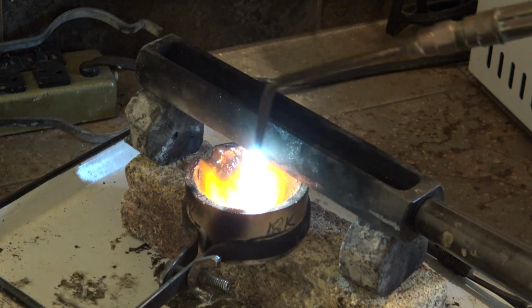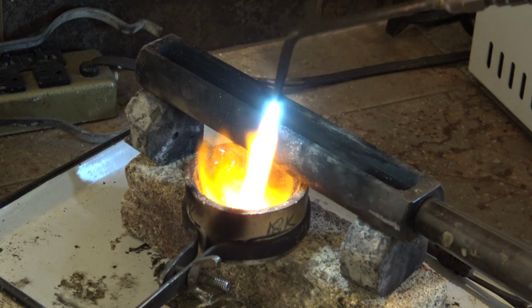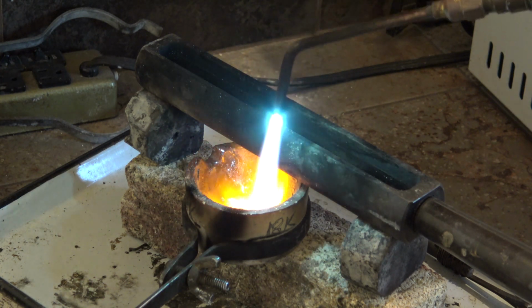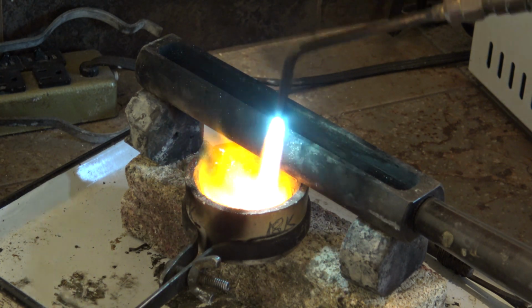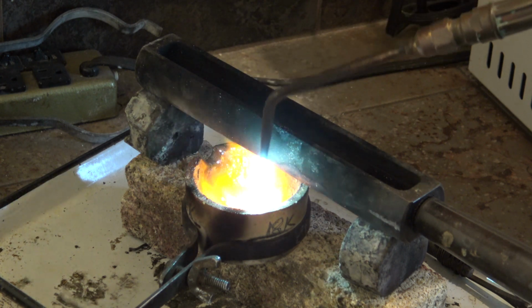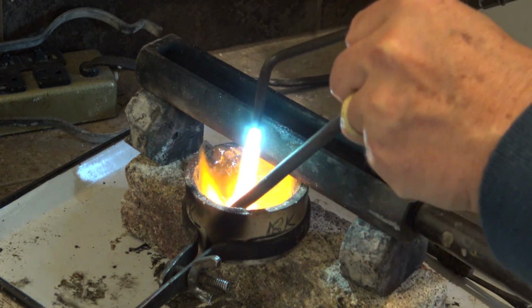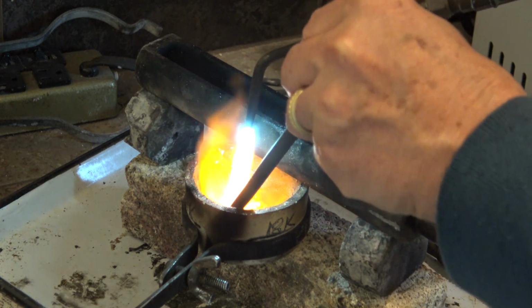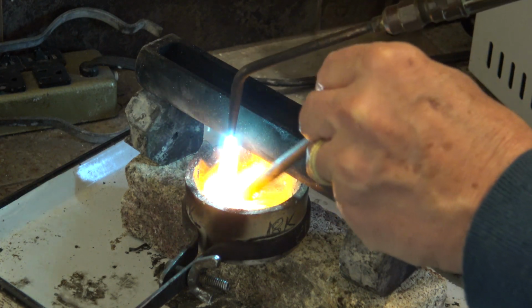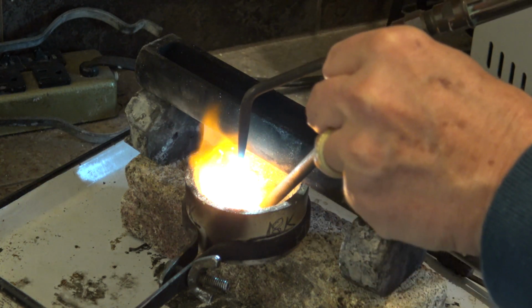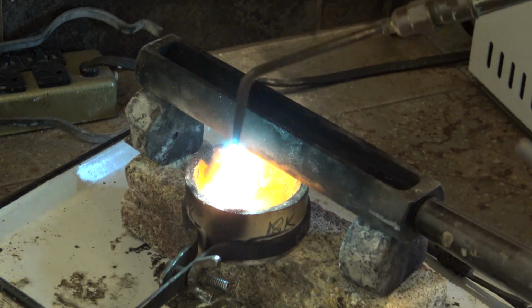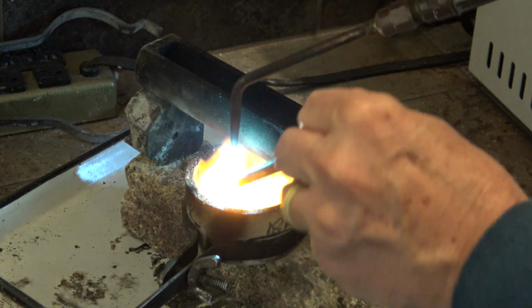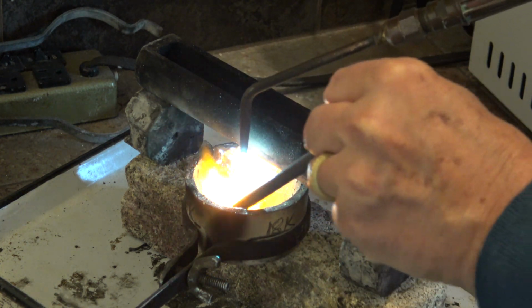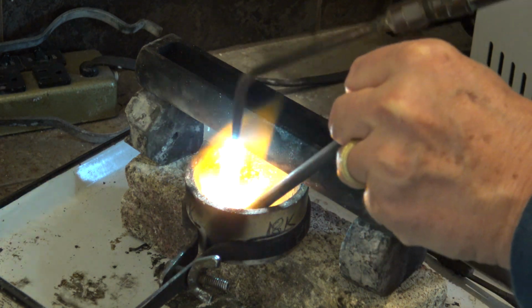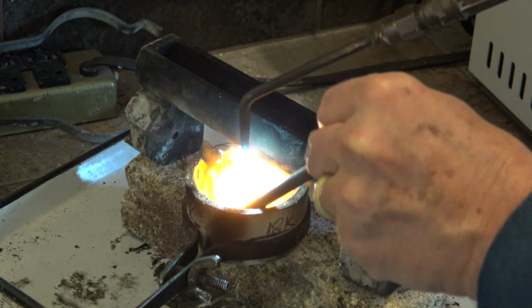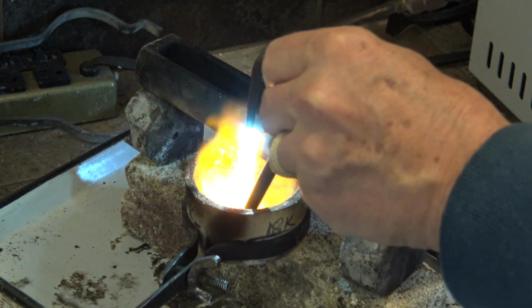At this point, I'd like to tell you about my ingot mold setup. You'll see that I have it raised above the crucible so that as I'm heating my metal, I can warm the ingot mold. I usually use beeswax to lubricate the mold before pouring. I don't need to use it every time, but I find that it works great for producing a nice shiny ingot. So my scrap is now almost a full puddle. I'm stirring it now with the rod.